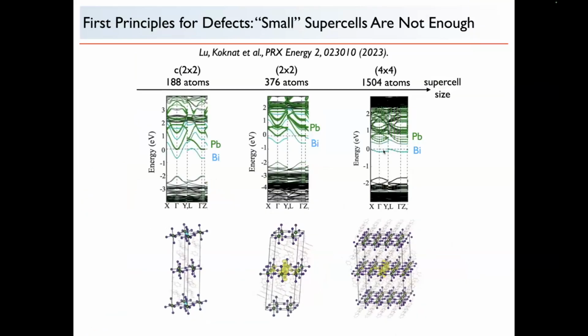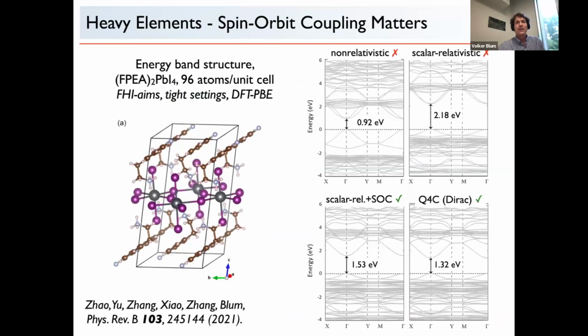Yes. And one critical point is that with smaller supercells, we would not get the flat band. So this is the 1504 atom supercell again, that you saw on the previous slide. But if you did this with a supercell that also seems respectably large, like 376, or even the smallest one here, 188 atoms, you see that these bands are much more dispersive, and so they're not well separated, and you don't get the properties of an effectively isolated defect.